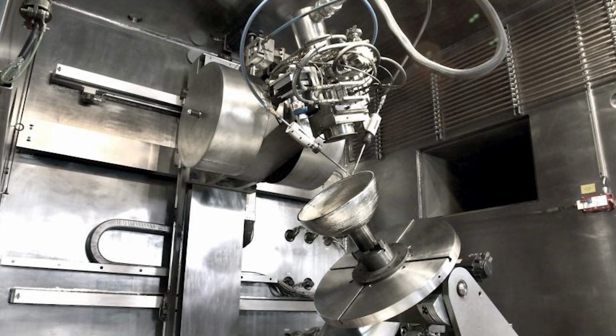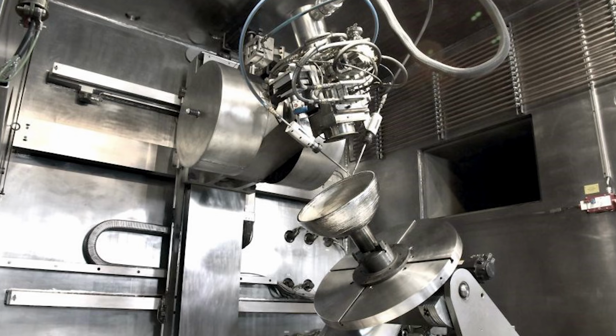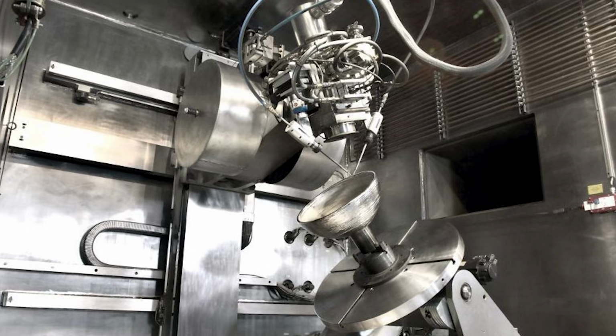Overthinking. Yeah. I mean, people came up with this electron beam based, very sophisticated method because it has some advantages. One is because you are doing the printing in an inert environment, the oxidation is low and the scatter of the electron beams is low, which leads to less oxidation, and the powder can be reused, whereas in powder bed fusion the contamination of powder happens more with the laser beam, so the reusability is low. Plus, because it's an electron beam and the way the setup is made, you can do very fast scans. A few meters per second could be the scanning speed, which is faster than laser. In powder bed fusion you would usually go to about 1-2 meters per second. With electron beam melting, you can go even higher than that.